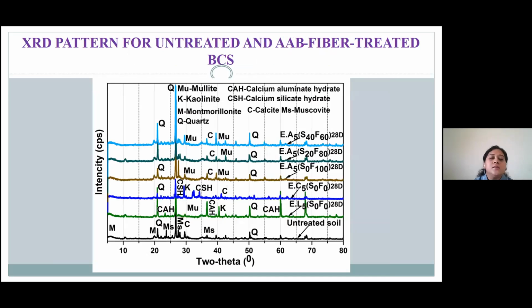I'll give glimpses of the different microstructural studies which we have performed. This is the XRD pattern for the untreated and the AAB fiber treated soil. XRD is used to determine the mineralogical composition of the soil. This XRD is obtained in powdered form, on powdered samples from 0 to 80 degrees at 2 seconds per step, using CuK alpha rays with 40 milliamperes at 40 kilovolts.